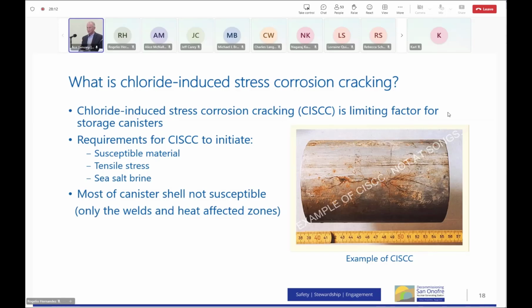Said it 3 or 4 times. We don't try to prevent salt. What we do prevent, though, is wet salt. You're going to see that our canisters are dry as King Tut's tomb. I may repeat that because that's the way I like to describe it. So as long as the salt can't get wet, you cannot have stress corrosion cracking. If you don't have tensile stresses, you cannot have stress corrosion cracking. If you don't have susceptible material, you cannot have stress corrosion cracking. Now, 316L is susceptible, but it's much, much less susceptible than 304. So we chose a much less susceptible material. It resists stress corrosion cracking a lot.